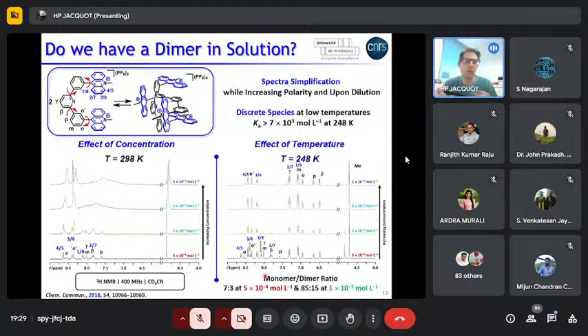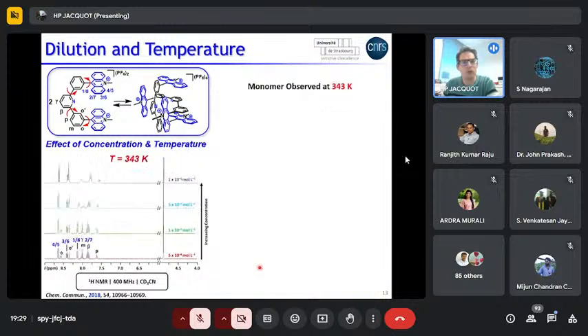So basically we can freeze the monomer-dimer equilibrium, and like this we can estimate a binding constant at low temperature. And we can do it also at different temperatures, and like this we can estimate the thermodynamic parameters of the system. So this monomer-dimer equilibrium was also confirmed at high temperature, because at the 4 previously studied concentrations, when you heat up the solution, you end up with almost the same spectrum. So this is expected since we work with weak interactions, and heating up will dissociate the assembly. So in our case, we have the monomer at high temperature.